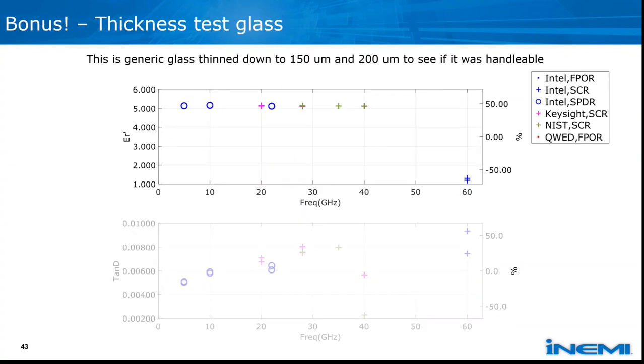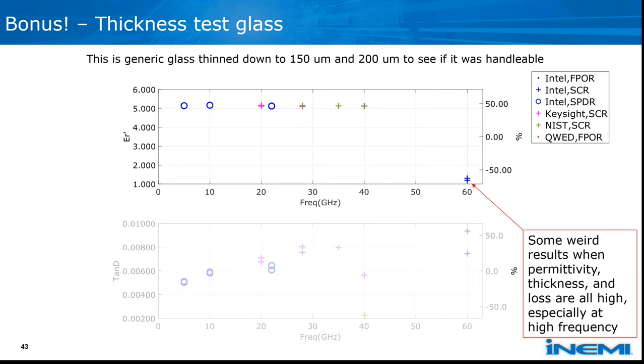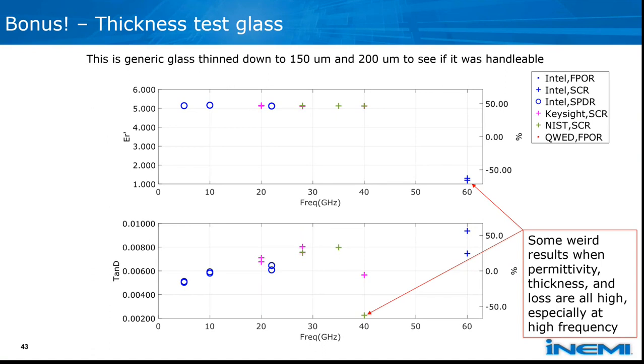We can skip through this. Essentially, I was just impressed that we could measure the thickness test glass, which was a less well-behaved microwave material. Even while really pushing the limits of these resonators in terms of permittivity, thickness, and loss all at the same time, we were still able to get pretty good results up to about 40 gigahertz. This just shows what happens if you really absolutely break your specifications on your resonators.